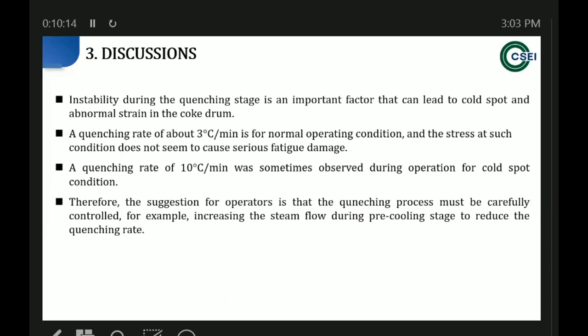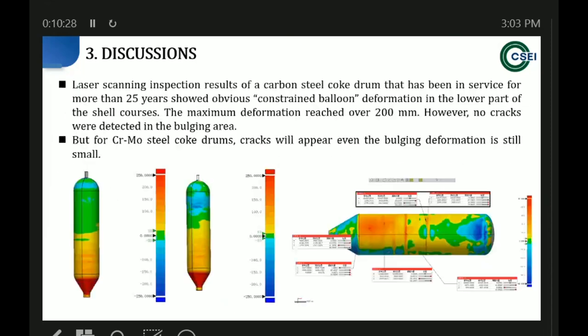So our suggestion is that the operator should carefully control the quenching process operation, for example increasing the steam flow during the cooling stage and reducing the quenching rate. And another thing we want to discuss is the relationship between the deformation and the crack.